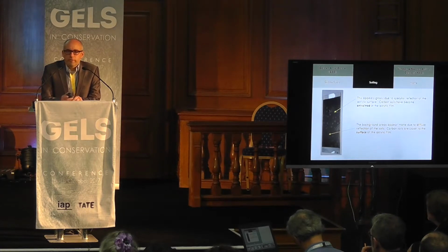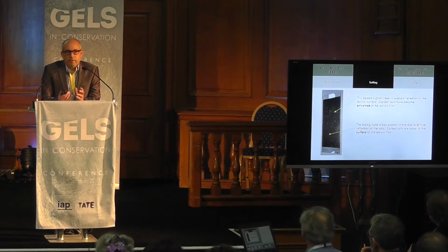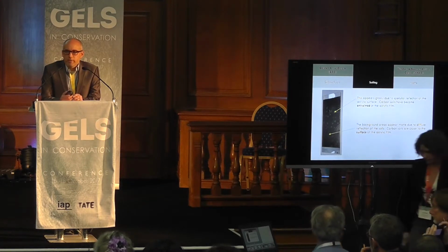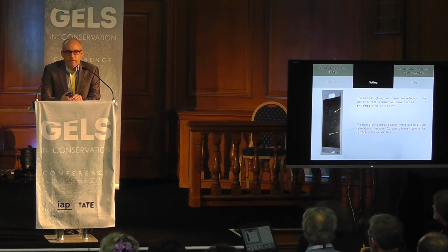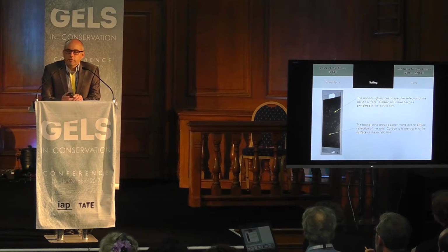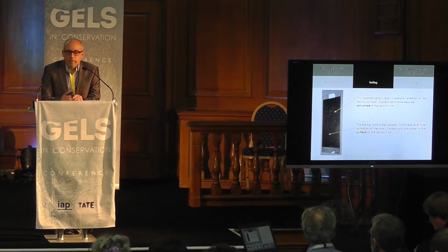We see specular reflection at the surface. What's happening here is that soils are being driven deeper and deeper into that paint film, and the surface of that paint film is becoming depleted of that soil. In the matte areas, the darker areas in this photograph, soils exist at the surface. We can see that there's diffuse reflection occurring here with the soils that remain at the surface. Those are going to be easier to clear. We knew that.